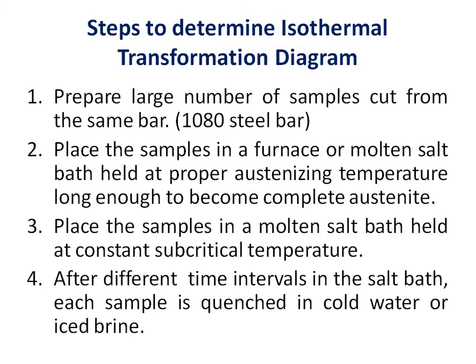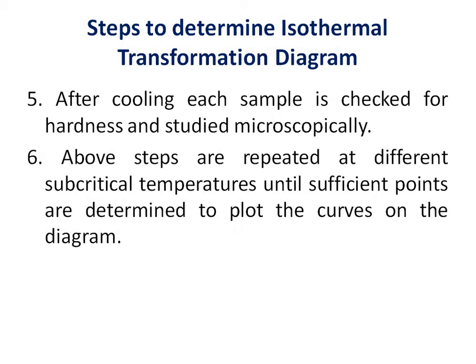Step number 4. After different time intervals in the salt bath, each sample is quenched in cold water or iced brine. Step number 5. After cooling, each sample is checked for hardness and studied microscopically. Step number 6. Above steps are repeated at different subcritical temperatures until sufficient points are determined to plot the curves on the diagram.